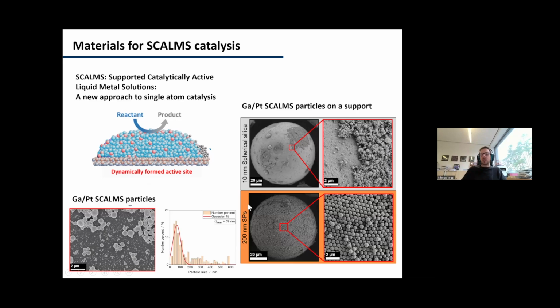And then we came up with this idea of using our superparticles. So this is what you see here. This is a typical catalyst support, and you see all the catalytically active particles reside on the surface. And since they turn molten, liquid under reaction conditions, they will start to coalesce and then lose surface area, and by this, activity. And in contrast, in our superparticles, you can hardly see anything, but you see these small particles that sit in the interstitial sites at the surface, and that means that they are trapped. And that means that they cannot move on the surface and do not coalesce, and that then increases the overall